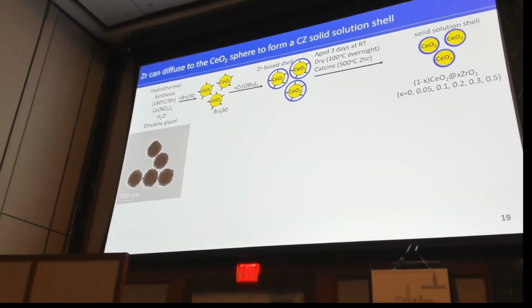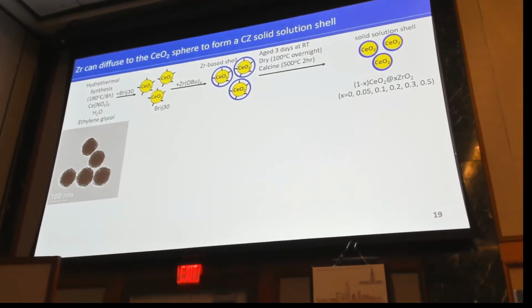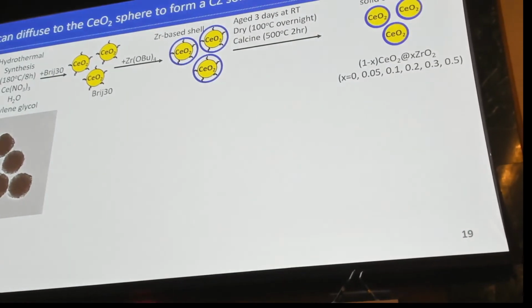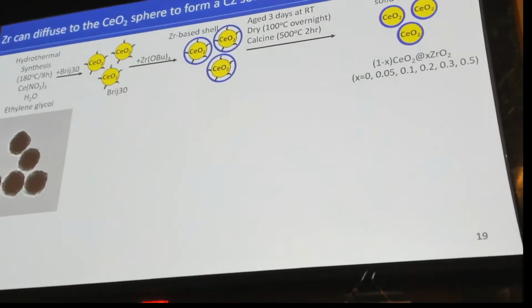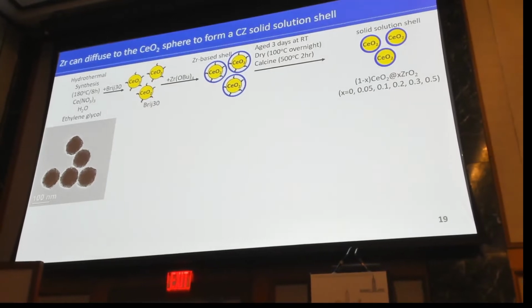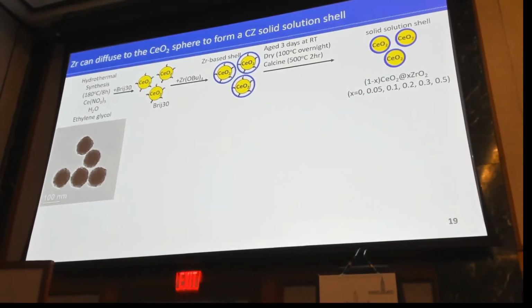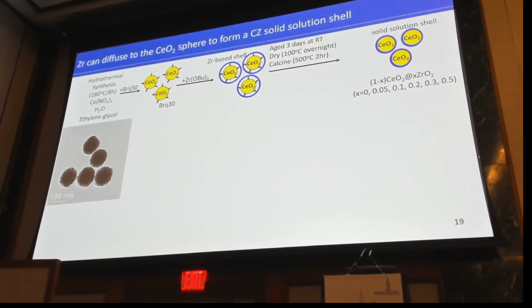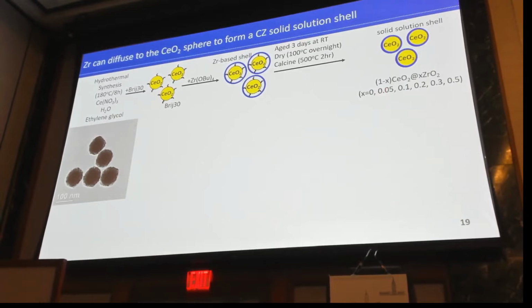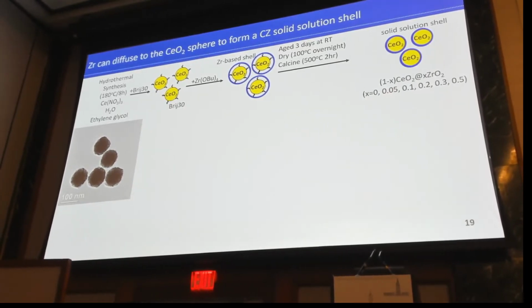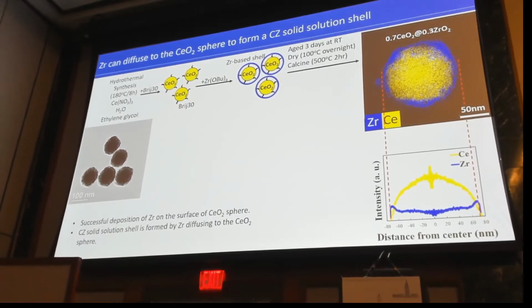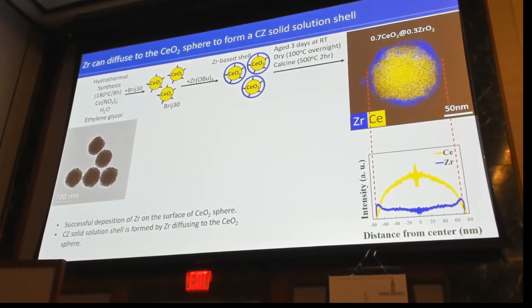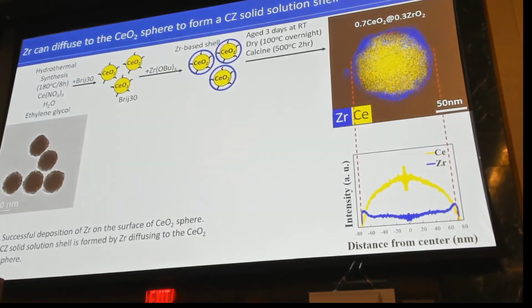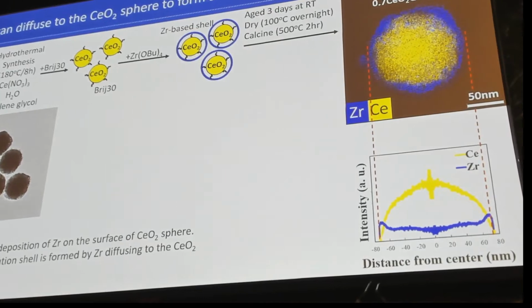So we have ceria in the core, and what we think we get is a shell that is a solid solution of ceria and zirconia. During this project, we decided also to vary the amount of zirconia, which is something that we also did in the first part of the talk. Here it changes the molar concentration of zirconium from 0, which is when we have just the ceria spheres, and then slowly increases the zirconium content from 0.05 up to 0.5. We were lucky enough to obtain EDS images from Michael Lane at Oak Ridge National Lab. Here you can see that ceria is the yellow and is deposited in the core, and we have zirconium, which is the blue, and it's in the shell.